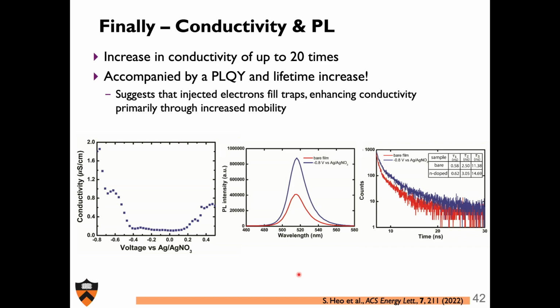This is going to allow us to make a great LED, a great laser diode. We've n-doped this system. The PL got brighter. That's great. And unfortunately, also, the lifetime got longer. And that's inconsistent with radiative recombination. If I'm doping this system, if I'm adding free electrons to it, my lifetime should go down when my PL goes up. But we did not see that. We saw that PL went up and lifetime also went up.